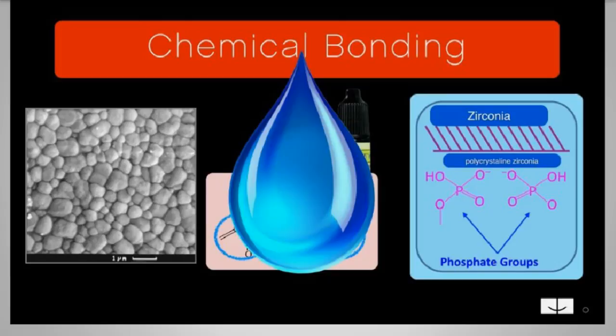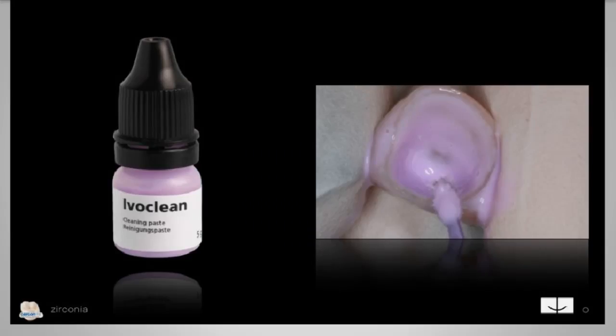One of the things that happened early on with zirconia, layered zirconia, your Lava crowns, was that people were using self-adhesive resin cements and they were coming off like crazy. And they didn't understand why. Why do my crowns keep coming off? What's the problem here? One of the things that happens, and this is why you would use Ivoclean, is the contamination of the phospholipids in your saliva, taking up the phosphate group that should be reserved for the resin.